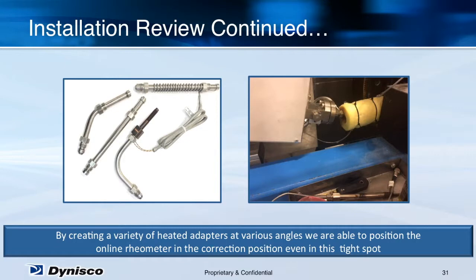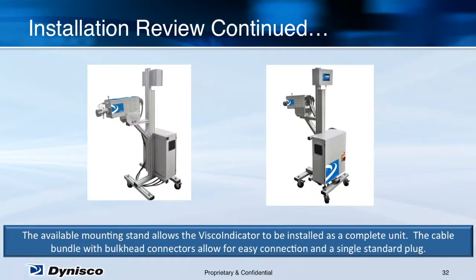One thing to note is that after the material passes through the rheometer and is evaluated, a small discharge stream, less than a half kilogram an hour, is dropped into a purge bucket beneath the unit. In this case, it happened to coincide with the same purge bucket that was underneath the underwater pelletizer connection. We developed the ViscoIndicator to have an easy mount stand and cable set that is a single one-plug 240-volt single-phase connection. This connection requires a quick and easy installation plan without costly specialized wiring. In a standard form, the unit can roll right up to the extruder.